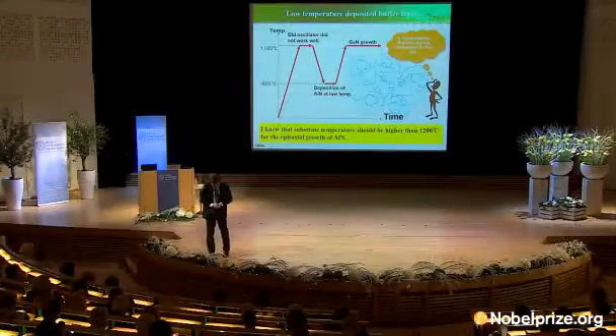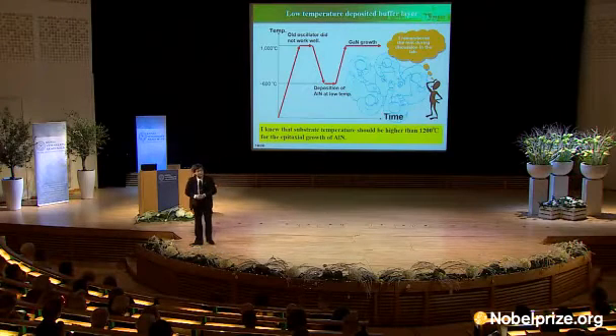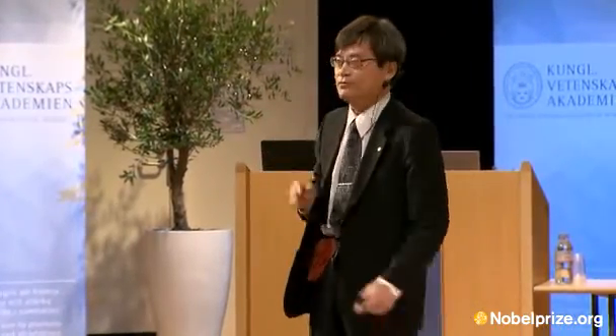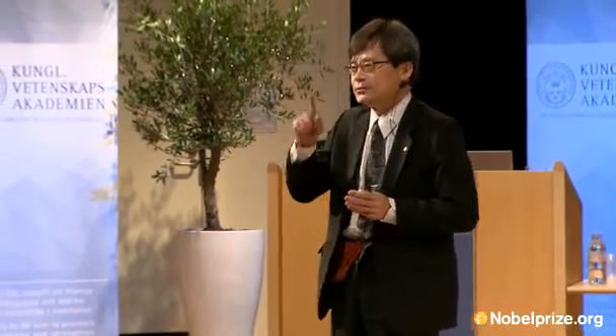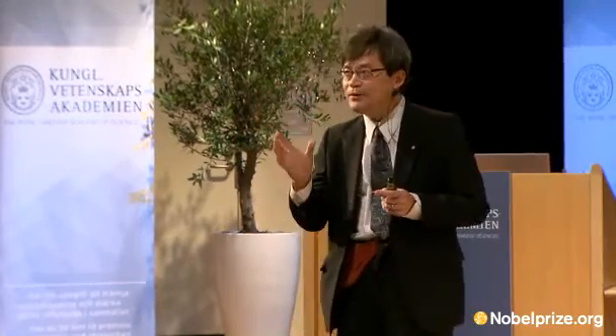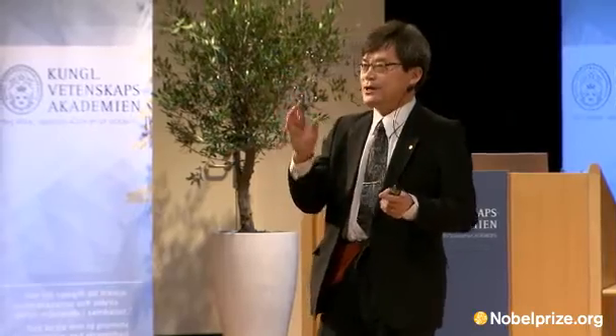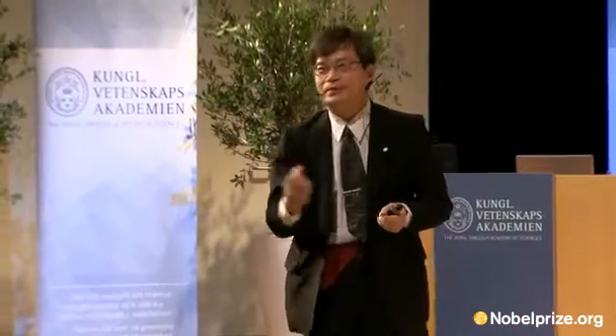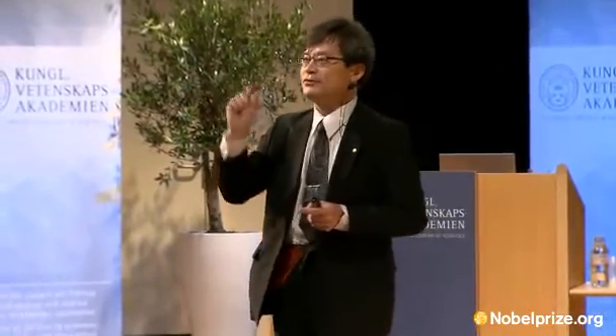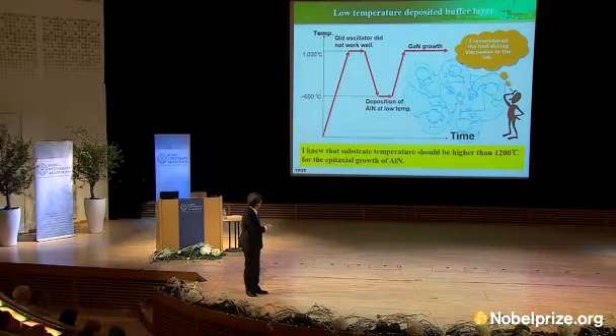Dr. Sawaki, the associate professor, mentioned that in case of boron phosphide on silicon growth, the lattice mismatch of which is as large as 24%, preflow of phosphorus gas is very effective to improve the surface morphology. And he claimed that phosphorus atoms act as the nucleation center. So I imagined that the low temperature deposition of aluminum nitride, very tiny aluminum nitride, should act as the nucleation center. Then I proceeded to the gallium nitride growth.